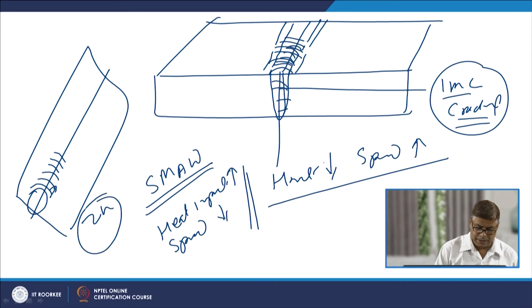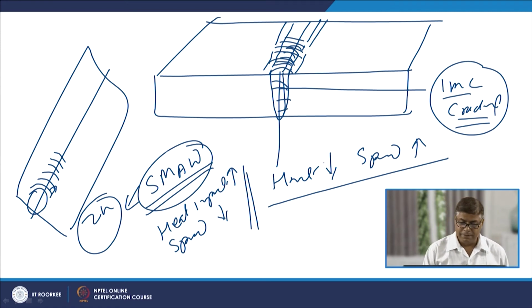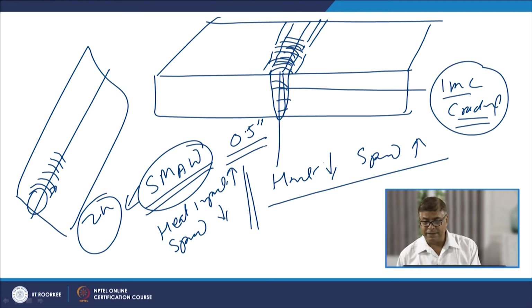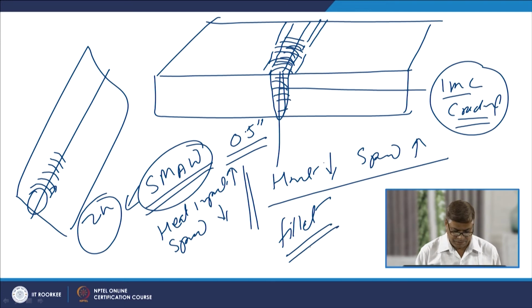So, the zinc concentration in the weld metal is reduced in case of the SMAW weld, and that is why it is able to tolerate the cracking up to the greater thickness, like say up to 0.5 inch, while less heat input and higher welding speed in case of the GMAW favors the greater concentration of zinc in the weld metal, which in turn promotes the intermetallic formation and the cracking tendency. So, no cracking up to 0.5 inch in case of the SMAW weld, as compared to the case when the cracking is observed significantly when the thickness is greater than 0.25 inch in case of the GMAW weld, and these cracks are more predominant in case of the fillet welds as compared to the butt weld joints.